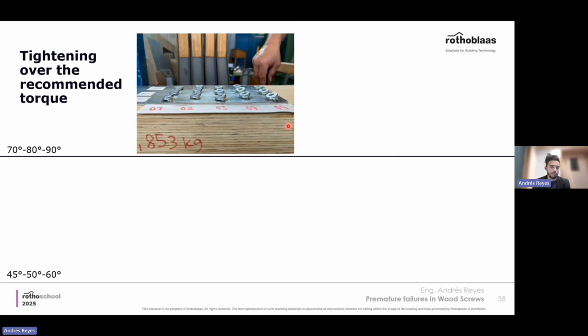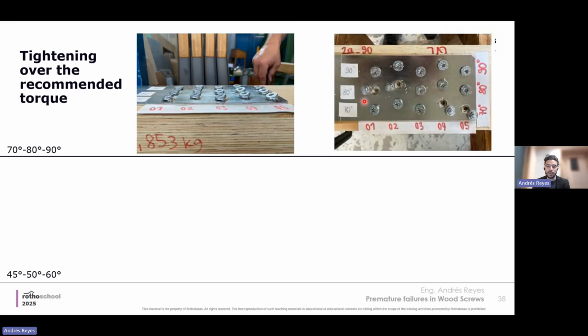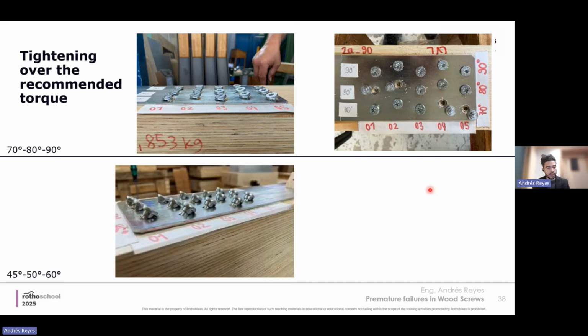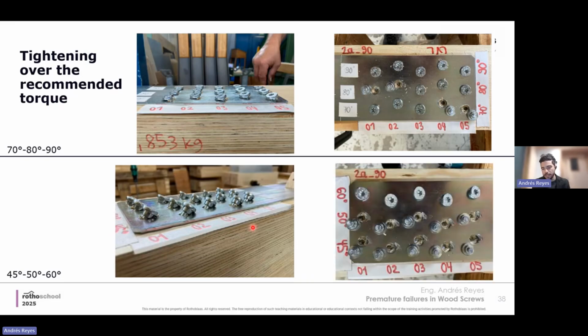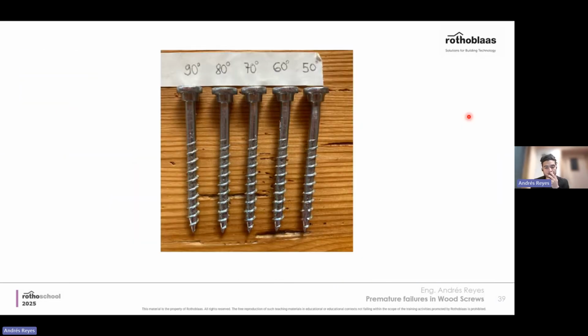But what can happen is that they break even during the installation. Of course, the higher the inclination, the higher the possibility for breakage. And here you see also 45 degrees, 50 degrees, 60 degrees, okay, the breakages happen more easily, of course, because it's an unrealistic inclination, I would say. Nonetheless, these ones are the most relevant, you see the effect. And you have some plastic deformations as well on the screws.